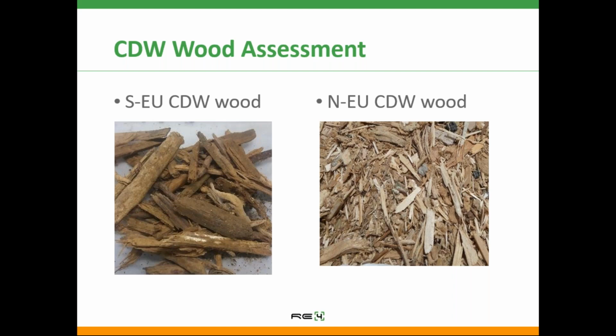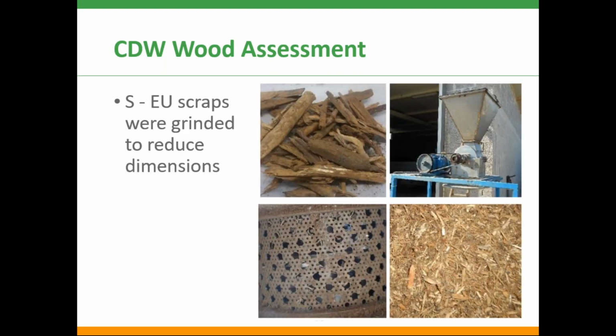As it is possible to see, the scraps were physically different depending on the provenance. Scraps coming from South Europe were bigger but more homogeneous in dimensions than the material coming from North Europe. Moreover, wood from South Europe arrived as pieces of dimensions in the range between 100 and 200 millimeters. For this reason, a further grinding process was necessary in order to reduce the material into fibers. A grinder with a sieve with a circular mesh of 20 millimeters was used. As far as wood from Northern Europe is concerned, it was delivered already in chips and fiber shapes, so no further grinding was necessary, but only a sieving step.